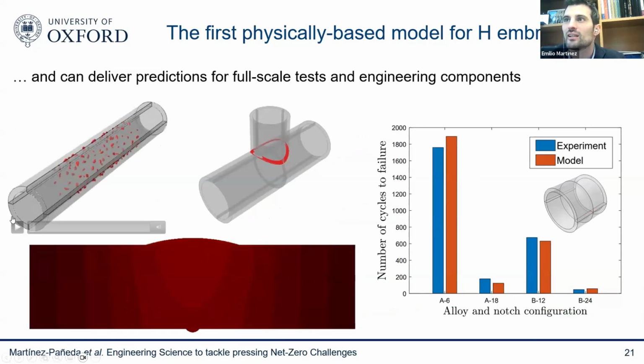This is a pipeline that contains, let's see if it runs, that contains hundreds of defects due to pitting corrosion. Those defects are going to grow driven by hydrogen. You can see how those defects are growing at the top, merging with each other, and eventually you get the complete failure of the pipeline.